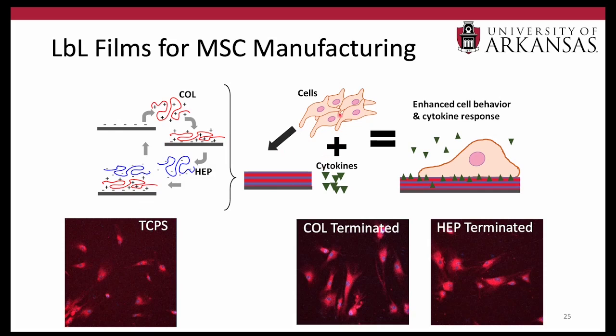And then we seeded cells on them, and then we studied the behavior of these cells with another important cytokine that I'll talk about here in a second. And these images that I am showing here are just to show you the cells, the MSCs, on our control polystyrene surfaces and on our multi-layers or layer by layer films that are terminated either in collagen or heparin. And this just shows you that morphology-wise, the cells look pretty good. They pretty much look just as good as our control.